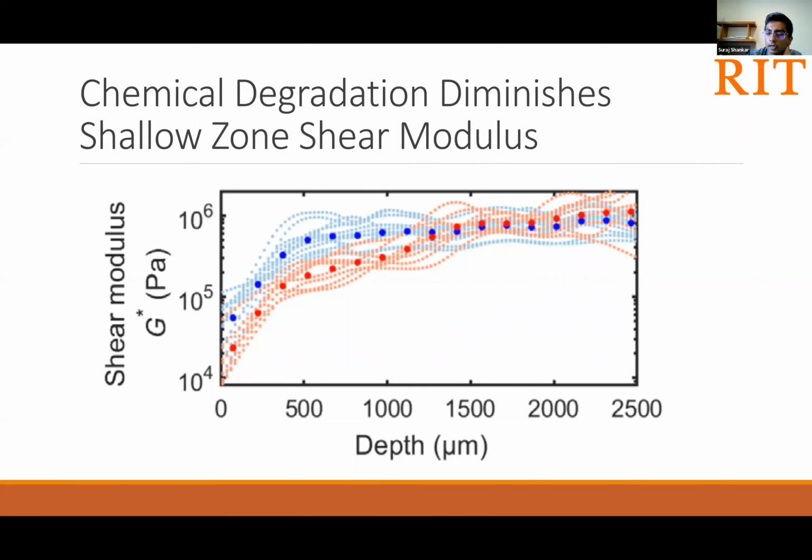I didn't prepare a lot of material about this, but our experimental colleagues looked at the real and complex components and found that while there was a non-zero out of phase loss modulus, it was orders of magnitude smaller than the storage modulus.